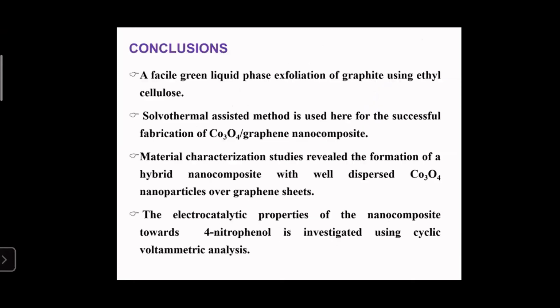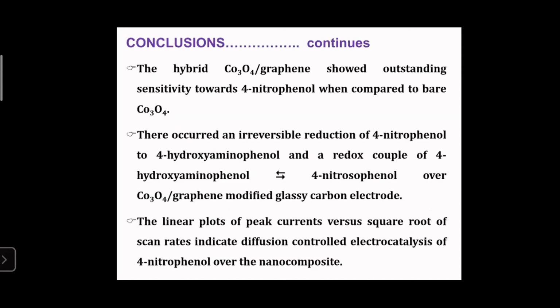And the major conclusions are, we have presented a facile green liquid phase exfoliation of graphite using ethyl cellulose. A solvothermal assisted method is used here for the successful fabrication of Co3O4 over graphene nanocomposite. The material characterization studies reveal the formation of a hybrid nanocomposite with well-dispersed Co3O4 nanoparticles over graphene sheets. The electrocatalytic properties of the nanocomposite towards 4-nitrophenol are investigated using cyclic voltammetric measurements. The hybrid nanocomposite showed outstanding sensitivity towards 4-nitrophenol when compared to pure Co3O4. We didn't study the response of pure graphene because the yield of the graphene after calcination at 400 degrees Celsius was very low.